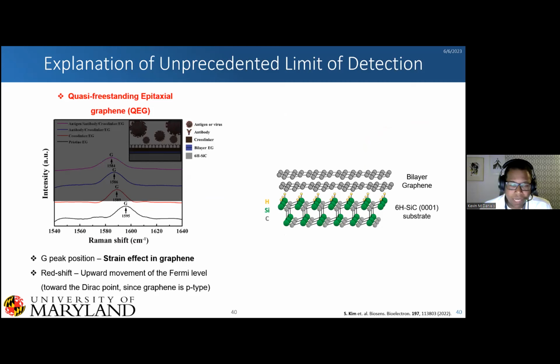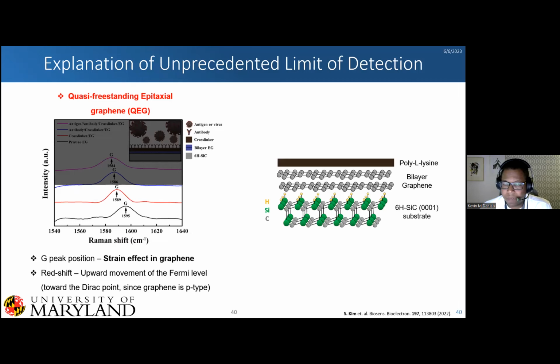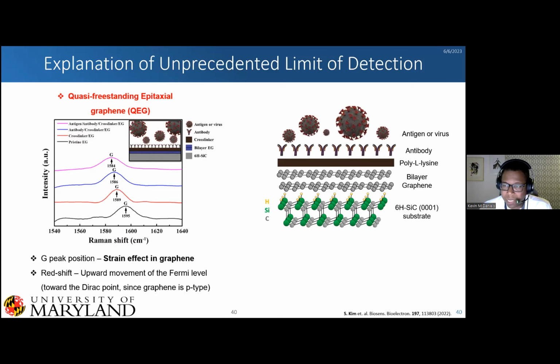And so we looked at the in-plane vibrational modes, or G peaks, which was sitting at 1595. Then we put down our poly-lysine, which is filled with amine groups, and that goes to 1589. We put down our antibody, it goes to 1586. And then when we put down our virus, so this is again an attogram, it shifts all the way to 1584.